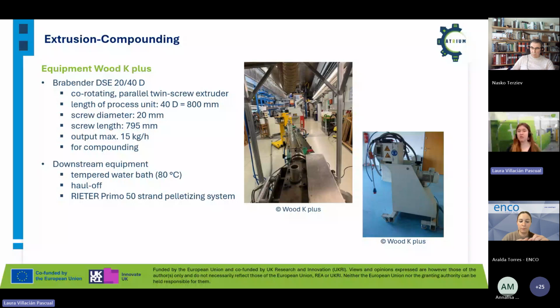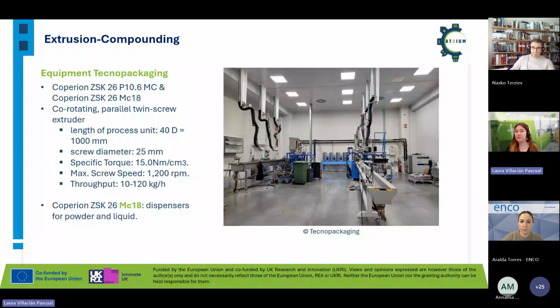In Technopackaging, we have two different extruders. In this case, the one that we are using is the Coperion MC18. This is the newest one, and we will be using this because it has dispensers for powder and for liquid as well. In this case, the extrusion compounding machine is a bit bigger than the one being used in Wood K plus. We are speaking about 1,000 millimeters instead of 800, and the screw diameter is a bit higher as well. It's 25 millimeters instead of 20 millimeters. This allows us to have a bit more mixing within the extrusion compounding.